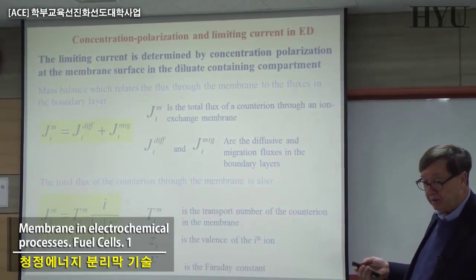Can we anticipate and predict this kind of phenomena? Exactly in the same way, nothing different as concerns the concentration polarization that you have already been discussing and studying in reverse osmosis, in gas separation, and similar. Basically, what you can do here is calculate what is called the limiting current, mentioned in fuel cell, here mentioned in electrodialysis, which is exactly the same story. Limiting current is the current at which there are no ions arriving at the interface where the phenomena take place. If the transport across the membrane is faster than the transfer from the bulk of the solution to the interface, at one point there will be no ions to be transferred across the membrane.